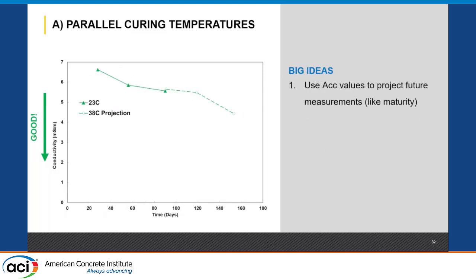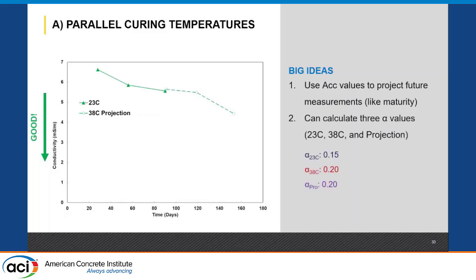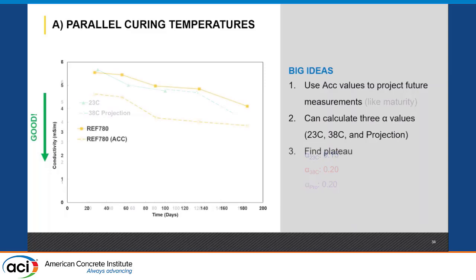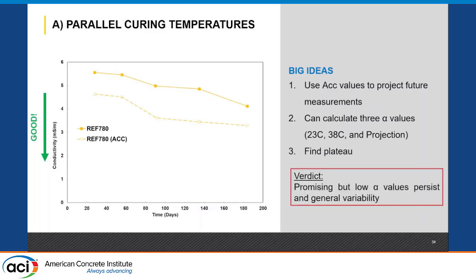Maybe you can get 150-day results in 90 days and so on. And you can also get a bunch of new alphas because you have new lines. And you can find when the pozzolanic reaction from the slag flattens. In general, that was promising, but we still had these low alpha values, and there was a lot of variability. I'm just showing you the plots that look kind of nice.